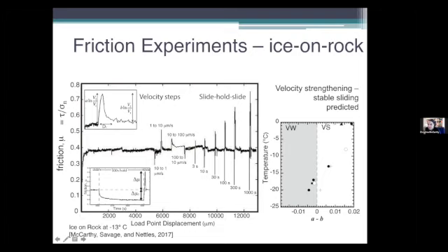So that's where you're basically chugging along at one constant velocity, in this case 10 microns per second, but then you will stop the piston. And so if over here on this inset, shown in time, here you've been having a steady state friction, you stop the piston, the system relaxes, the friction relaxes for some amount, and then when you restart the piston, the friction jumps up.